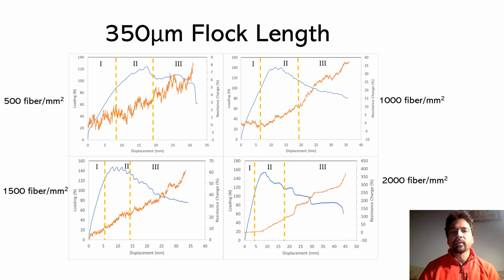Hence, you see a maximum of less than 10% change in electrical resistance in the system of 500 fibers per millimeter square. However, if the flock density is increased to 1000 fibers per millimeter square, you see a gradual increase in resistance and there is very little noise too. But the maximum value is around 40% change in resistance, which is expected because the electrical network is much better compared to 500 fibers per millimeter square. As you increase the flock density to 1500, you can see that the maximum resistance change as the crack is propagating along the system is around 60%, much improved compared to 1000.